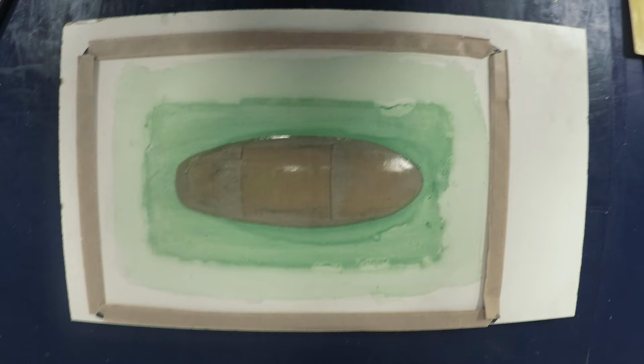to both parts. The last step in mold preparation is to place down the tacky tape used to form the seal between the mold surface and the vacuum bag. When placing down this tape, it is best to do it before any wet epoxy can be spilled on the surface, which can prevent a good seal from forming between the surface and the tape. Be sure to press down firmly on the tape, especially over any locations where the tape joins other strips of tape.